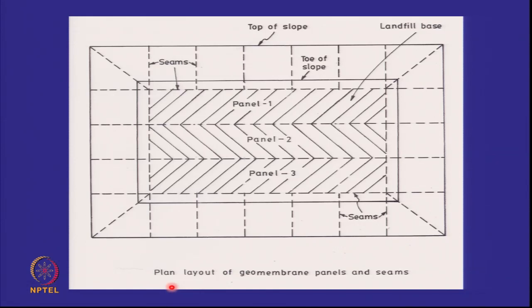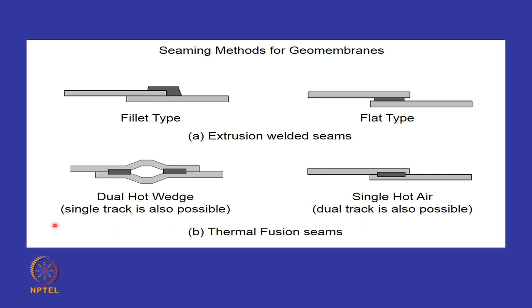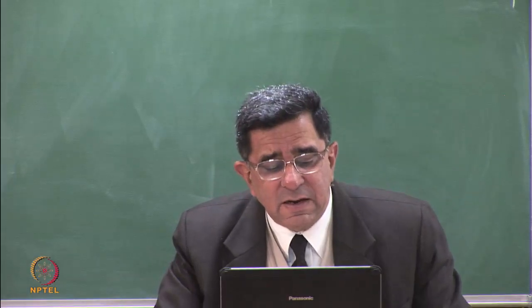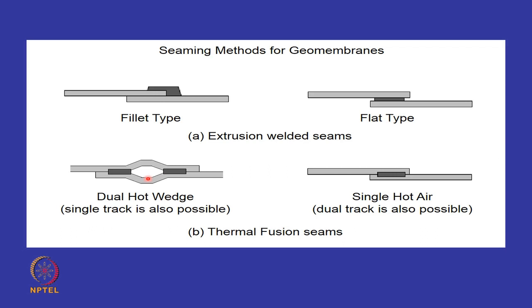So I only showed you the plan layout of a geomembrane panel and where the seams will be made. And these are some of the type of welds. These are extrusion welds. You're putting extra material on the overlap or in between. And these are thermal fusion welds. So the weld which is done in most geomembranes is this one. It's called a dual hot wedge weld. You weld it in such a manner that there's an air gap at the center. And basically just heat it and weld it.